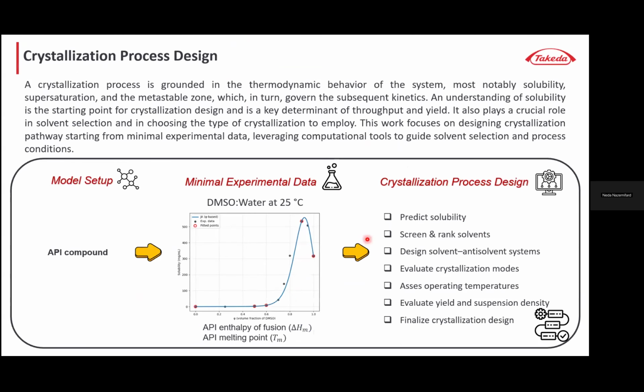This slide shows the thermodynamic starting point. Crystallization design is really anchored in solubility, supersaturation, and the metastable zone. If this foundation is solid, we can have a very robust crystallization design from the beginning. So the question we are asking is: can we design a viable pathway from minimal experimental data for a new API? If I know the structure and a few key properties, such as melting point and enthalpy of fusion, I can already start predicting solubility behavior, screening solvents, estimating yield, and looking at slurry density. Then I use a limited amount of measured data to calibrate the model, as I said before. The point is not to believe the model blindly, but to use it early enough to avoid locking into a solvent system or operating window that is fundamentally working against the outcome that you want.